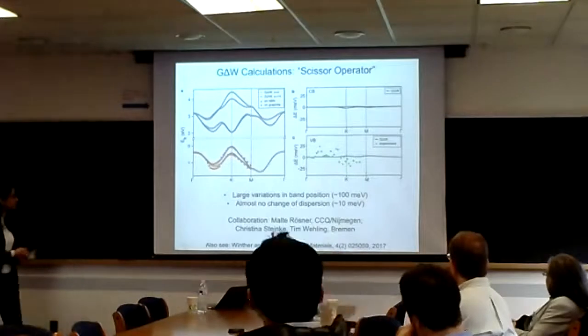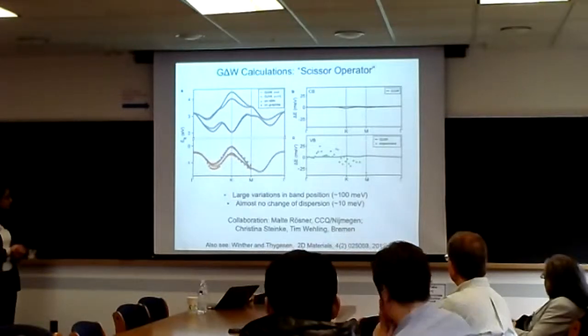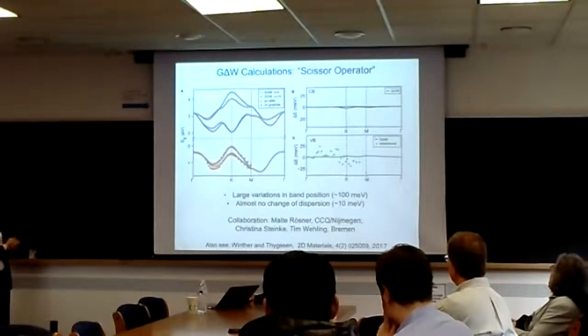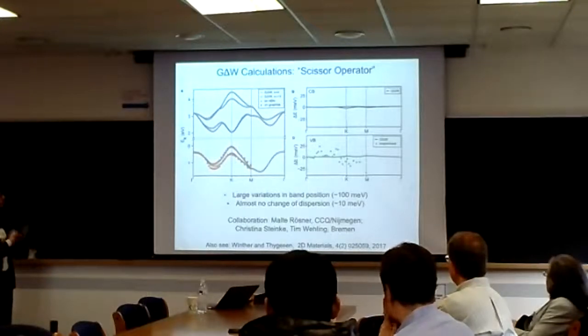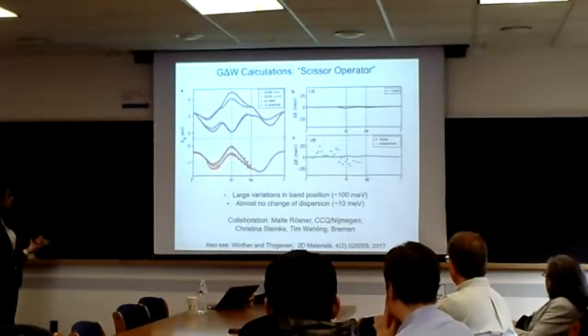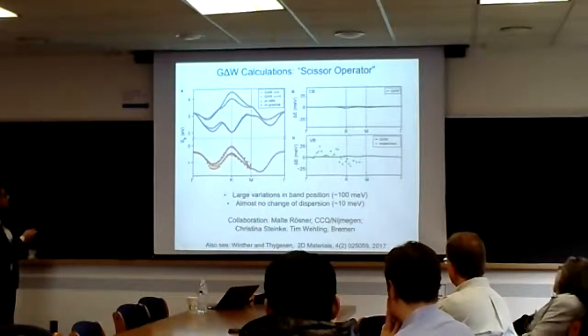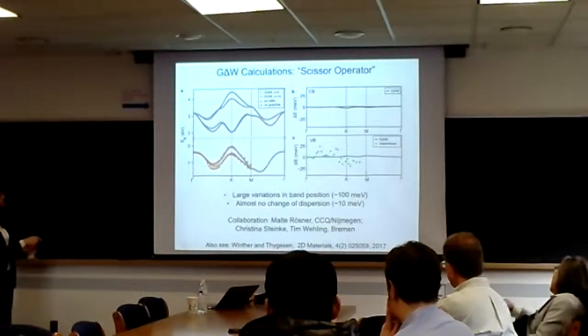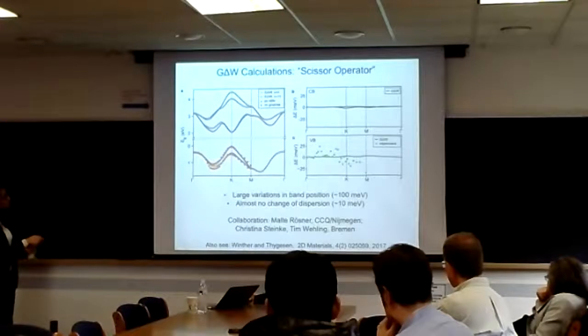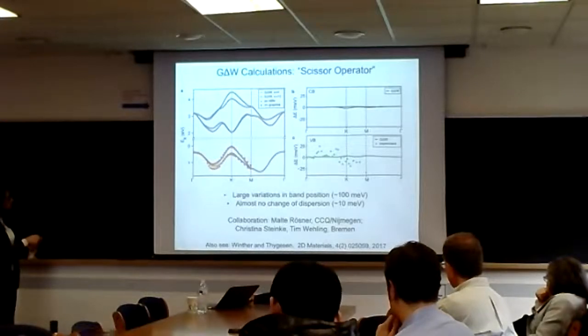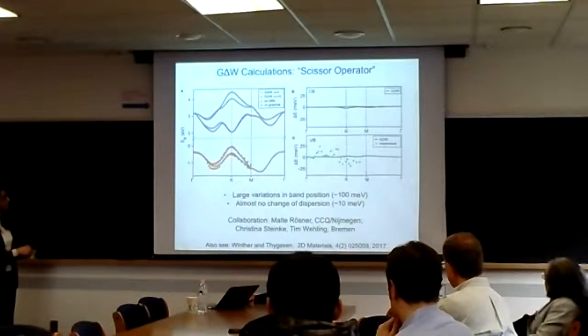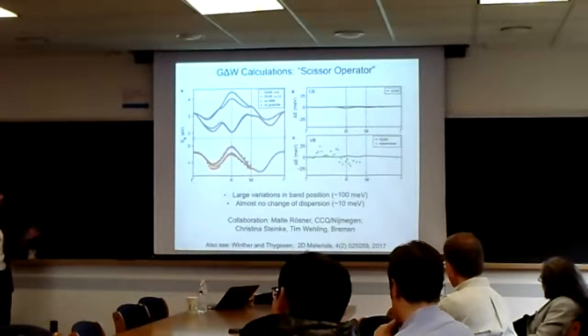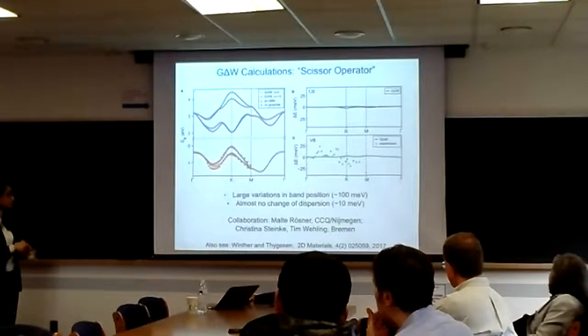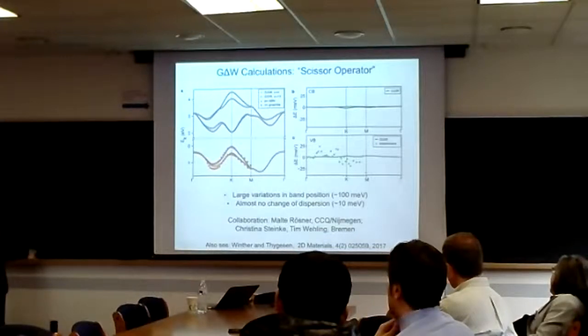So we collaborated with Tim Wehling's group, and our main collaborator here is Malte Rösner, who used to be at CCQ, and he calculates in the G delta W approximation, where we use an effective dielectric function. For different screening, the band structure itself again doesn't really change in theory between the grayish blue and the grayish orange, and we're just plotting our experimental results on top here. The bottom line is that you can have very large variations of the band gap purely due to screening, and almost no change of the dispersion within 10 meV.